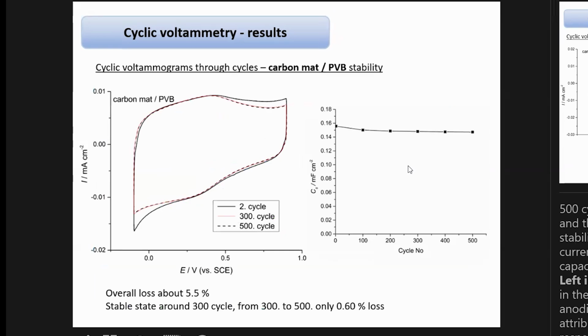Also, it is important to observe the stability during many cycles of the test with this method. First, the diagram on the left shows that we have performed 500 cycles of the test, and in this diagram we have the results for the second cycle, and after 300 and after 500 cycles. It is interesting to note that there are practically the same results after 300 and 500 cycles. There is a difference between the second and the 300th, but the overall loss is not high. It's only 5.5%. And then from 300 to 500 cycles, only 0.60% loss